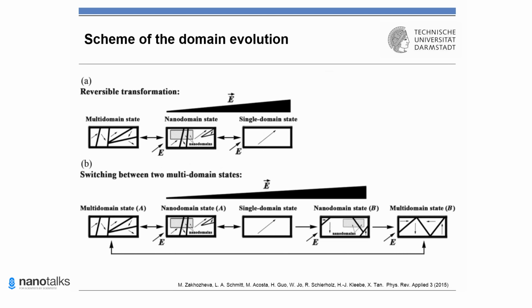Okay, based on our results, we propose such a scheme of domain evolution. Here you can see one grain with the domains. During applying an electric field, we have a transformation from multiple to single domain state. In some material, it happens that the nanodomain state occurs in between. This situation is completely reversible. On reducing the field, we see a multiple domain state again.